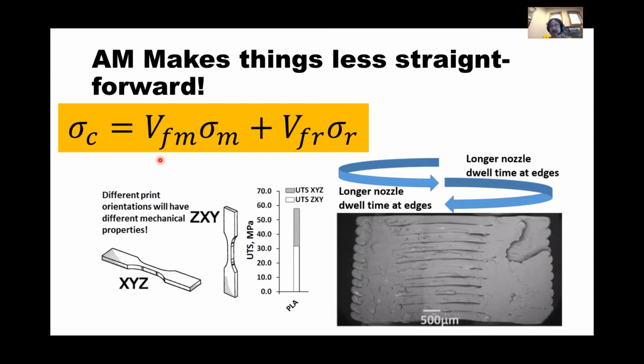In the area of composites, characterizing AM or additively manufactured parts is less straightforward—it's not just a matter of this equation. Different print orientations will have different mechanical properties. If you print it flat, it's going to be stronger than if you print it vertically, and that's because of failure at the inter-raster interface. Improving that interface has also been a subject of our work, and we'll talk about that a bit.